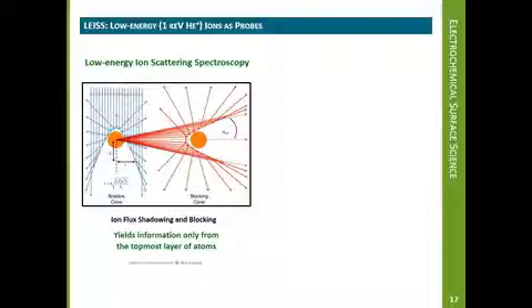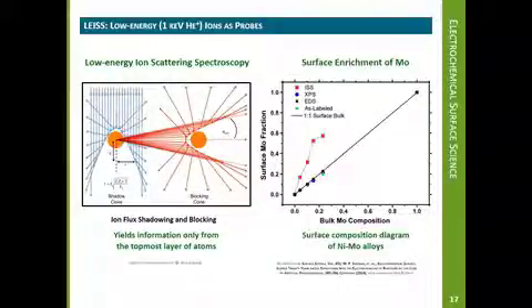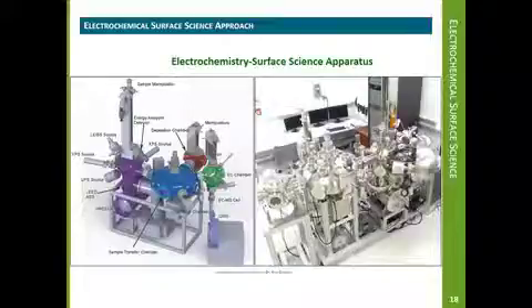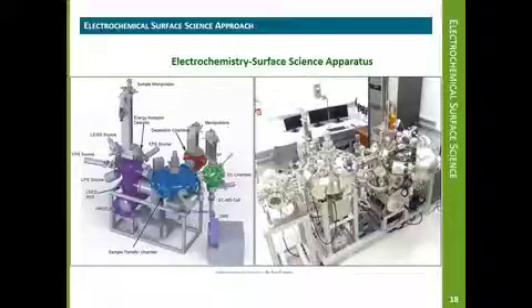In this example, the surface atomic fraction of molybdenum was compared with that of the bulk. If the surface behaved as a bulk truncated plane, then the surface fraction of molybdenum would be expected to follow the black 1-to-1 line. Surface quantitation by X-ray photoelectron spectroscopy indicated this was the case. However, the molybdenum fraction was further quantitated by the more surface-sensitive ion scattering technique and the catalyst surface was observed to be highly enriched in molybdenum relative to the bulk. By employing as many surface-sensitive techniques as possible, trends can be revealed that might otherwise go undetected.